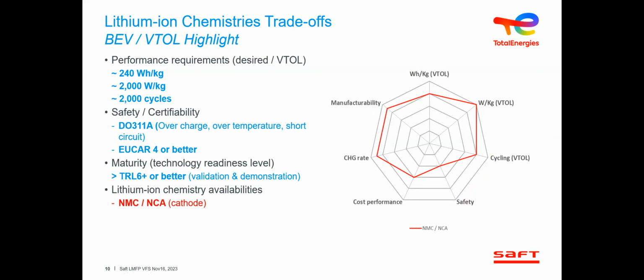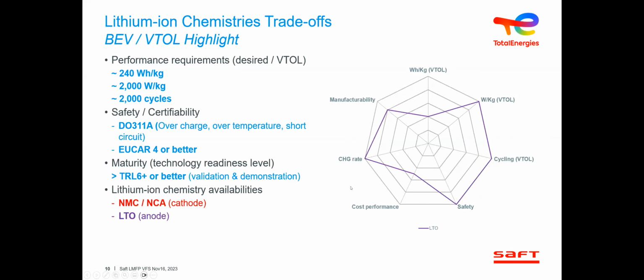If I take various chemistries that I'm going to go through one by one, the very commonly used currently are nickel manganese cobalt, or NMC, and NCA, nickel cobalt aluminum, which offer very high specific energy, specific power, good cycling ability, but unfortunately are more towards EUCAR 6 or 7 and exhibit poor safety, decent cost performance, chargeability is good, and the manufacturing ability is okay. On the chemistry on the anode side, the NMC and NCA is a cathode, so it is your positive electrode, your negative electrode being a carbon anode.